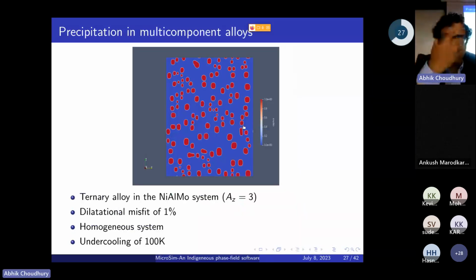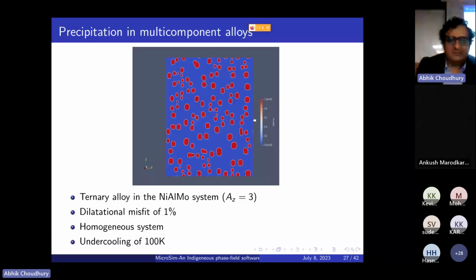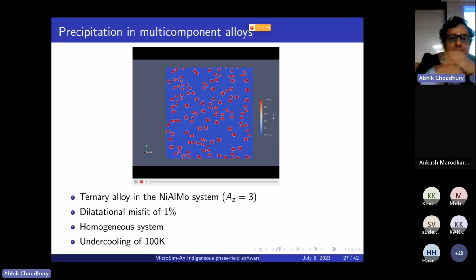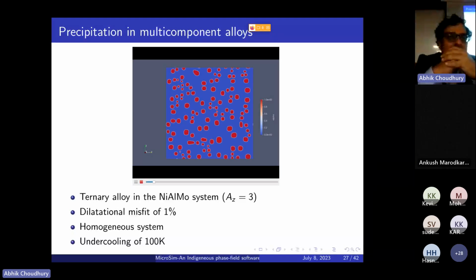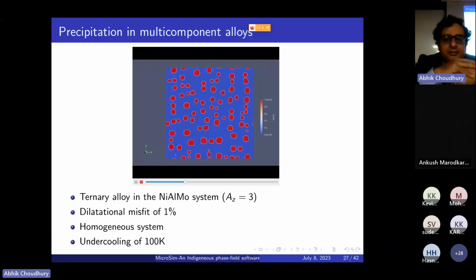So I'll go now to some of the updates that have happened in the last year. One of the principal updates has been the incorporation of elasticity in all modules. This is, for example, a coarsening simulation happening in the Ni-Al-Mo ternary system with the incorporation of a cubic elastic coherency stress. What you see is that you go into growth followed by coarsening, where some of the precipitates are growing and the smaller ones are disappearing in the coarsening regime.